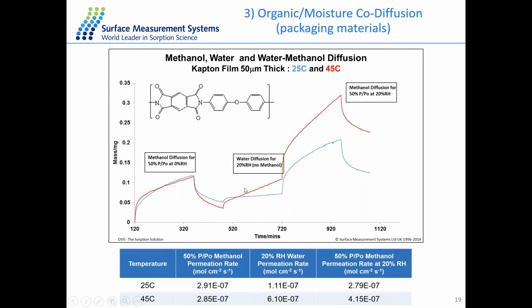However, for the second stage, which is the water-only stage, this time the value at 45 degrees is almost 5 times larger than at 25 degrees. This is probably because higher temperature encourages molecular mobility, which results in a higher diffusion for the water molecule. And for the last stage here, which is the methanol with the background humidity, the permeation rate at 45 degrees is also increased a little bit compared to 25 degrees.